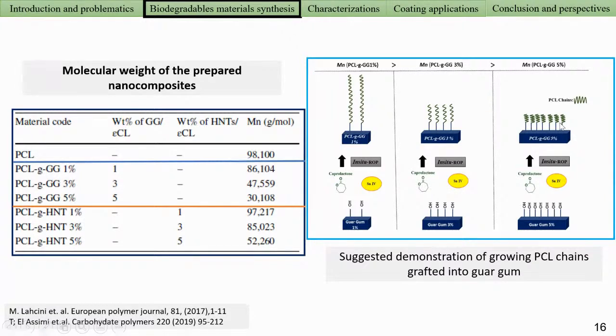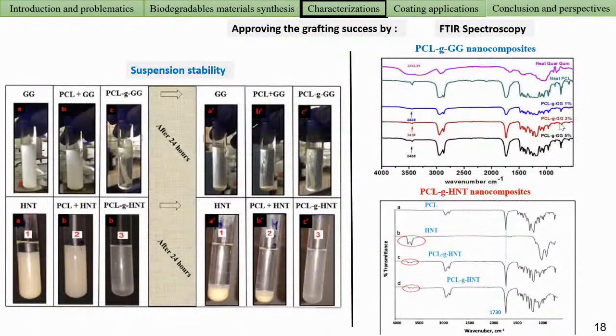But what we observe is that when we increase the content of fillers, the reaction is really fast. For example, with 5%, we need only 10 minutes, but with 1%, we need between 15 to 20 minutes. And to prove that we really graft the polymer on the surface, we first analyze the nanocomposite by IR.